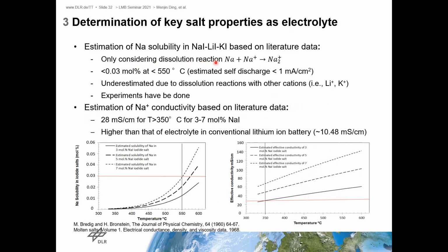According to the literature, below 550 degrees C its solubility is quite low, and the estimated self-discharge rate is also low enough. But the real value can be higher than estimated, maybe due to other dissolution reactions. The experiment has been done, and I will show you later.